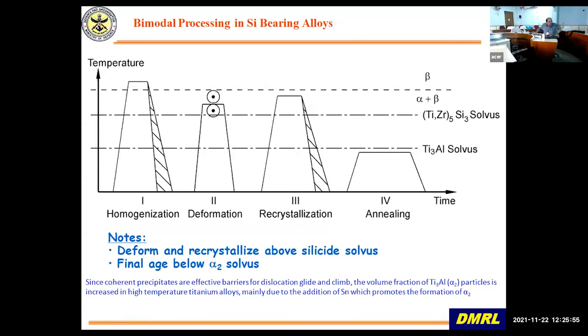So now, as compared to the alpha plus beta alloys, you see how these high temperature near alpha titanium alloys are slightly more complex. There are other solvuses that have come in. That is the silicide solvus, which is in the alpha plus beta, and there is also the Ti3Al solvus. Ti3Al you want if you want high temperature strength, that is the ordered alpha. Now, because these are intermetallic, you have to be careful where you deform and heat treat and all.